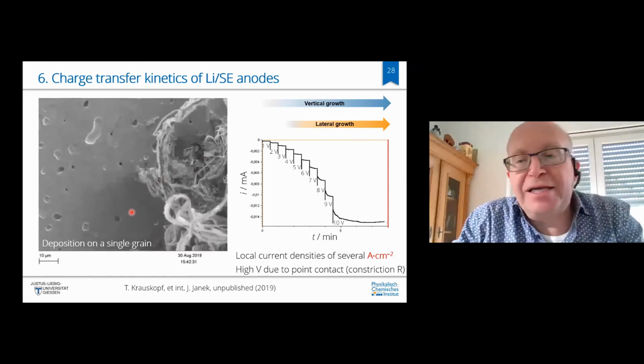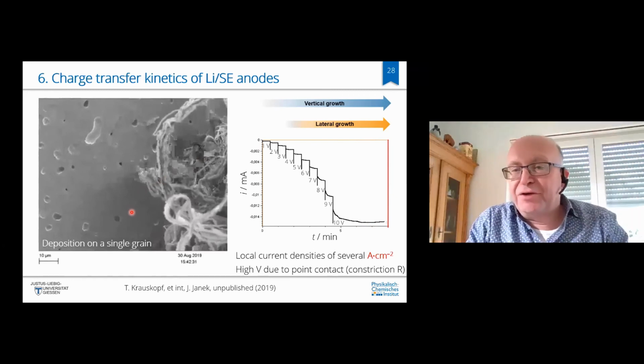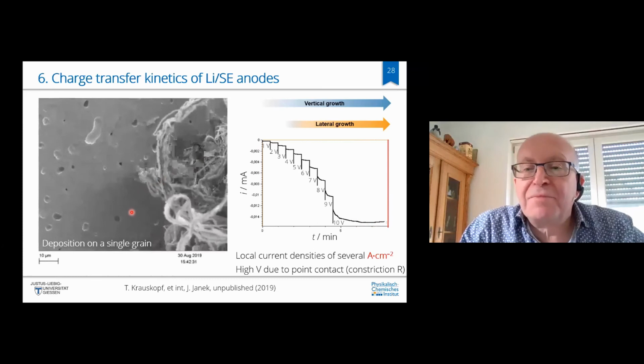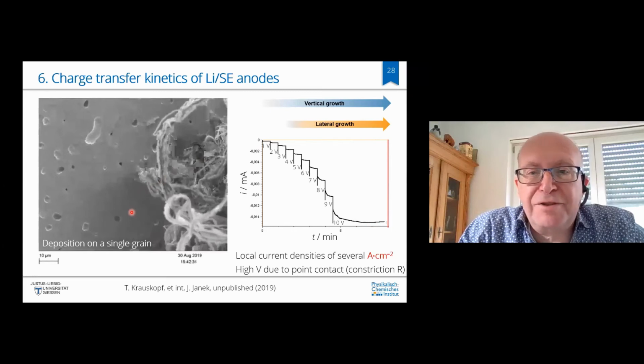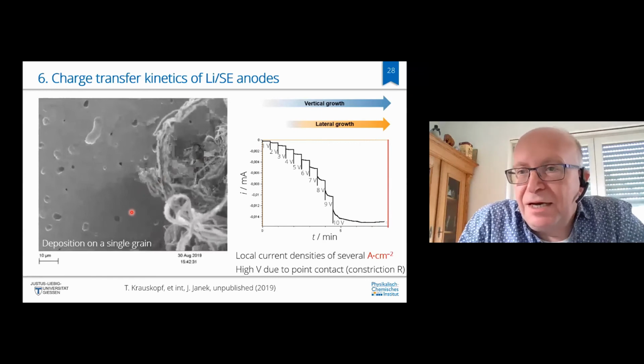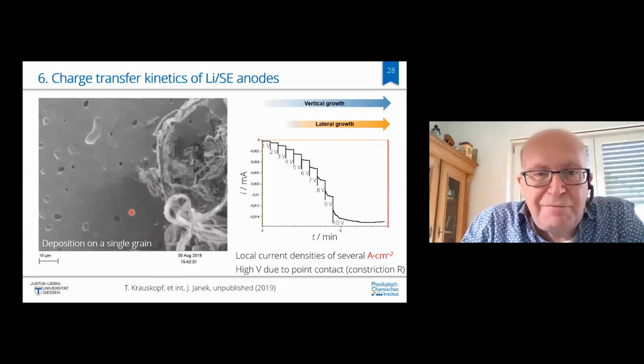And if we analyze the rate of growth and the contact area of these whiskers, we see that the current density of this lithium whisker growth on the solid electrolyte is in the order of several amps per square centimeter. So if you have a good contact, the lithium growth is not limiting. But the morphology is critical, of course.